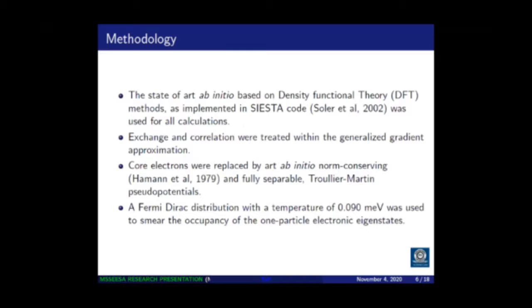Now, the methodology I adopted here: I used the state of the art ab initio methods based on the density functional theory implemented in the SIESTA code. The exchange correlation was treated with the generalized gradient approximation, and the core electrons were replaced by the ab initio norm-conserving fully separable Troullier-Martins pseudopotentials. And the Fermi-Dirac distribution with a temperature of 0.09 milli-electron volts was used to smear the occupancy of one particle eigenstates.